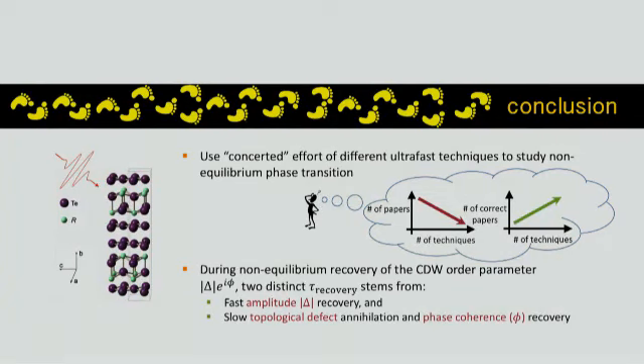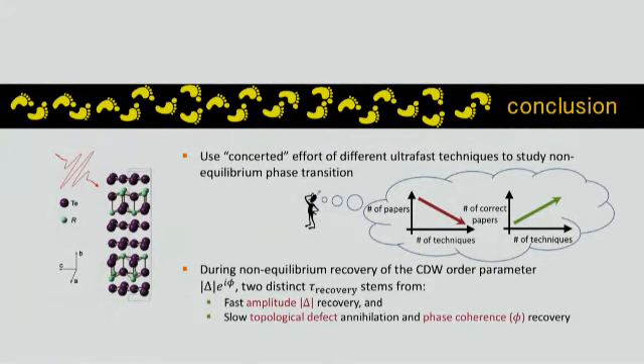So why should the amplitude recover faster than the domain size or the phase? Yeah, one idea that we have is that for the domain to get annihilated, to some extent it's a topological defect, so it takes a lot of energy to annihilate a domain, where you have to have the domain walls propagate and two domain walls merge. Then you have an annihilation of domain walls, which is more energetically costly to recover.